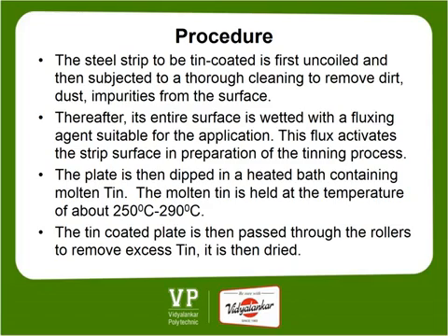The plate is then dipped in a heated bath containing molten tin. The molten tin is held at a temperature of about 250 to 290 degrees Celsius. The tin coated plate is then passed through the rollers to remove excess tin. It is then dried.